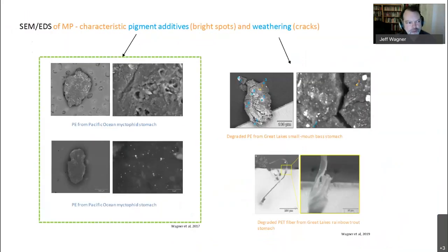For my last couple of slides, I wanted to show some of the utility for SEM for microplastics, although the EDS component is pretty much mostly useful for identifying chemically the chlorine-rich polymers, such as PVC. But morphology-wise, there's a lot of interesting things you can determine with SEM. For one, that kind of characteristic manufactured material property that I mentioned earlier with the uniformly distributed inorganic plastic additives. In the two examples on the left, those didn't turn out to be flame retardants, but rather other common additives such as titanium dioxide or calcium carbonate, common plastic fillers.